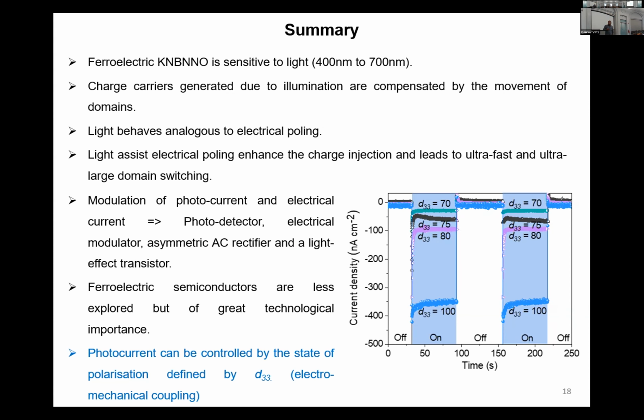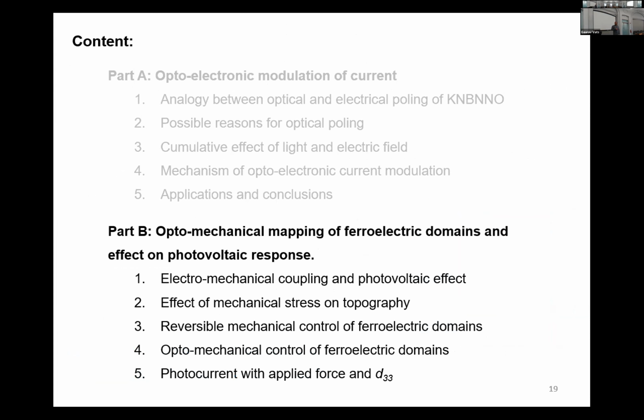So yeah, and another interesting thing is photocurrent can be controlled by the state of polarization in D33. So if you look at this figure, I poled the sample at different parameters where I could observe different D33. And then I checked photocurrent in these samples. The photocurrent is different in different samples with different polarization. So this is interesting. And when we talk about D33, basically we are talking about electromechanical coupling. And that's what I'm going to talk about in part B of this talk. So let's move on to part B.